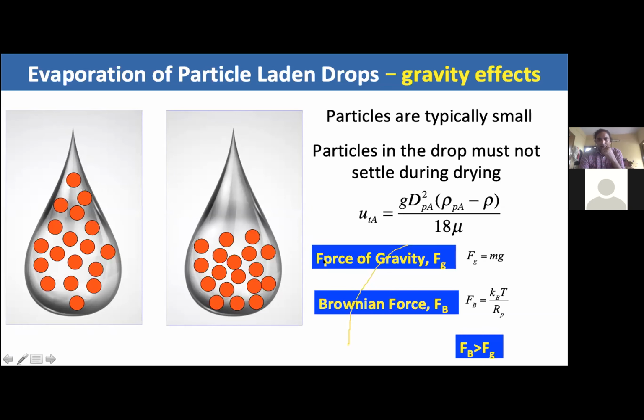occur. The gravitational force Fg that is acting on the particle is given by m times g, and the Brownian force is given by kBT divided by rp. So one has to ensure that the Brownian forces outweigh the gravitational forces acting on the particle. That can be easily met when we are dealing with small particles. Therefore, the gravity effects which lead to sedimentation of the particles can be avoided.